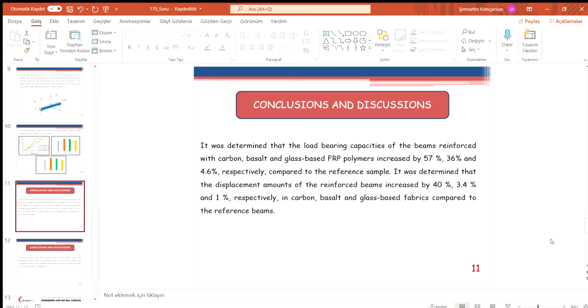It was determined that the load-bearing capacity of the beams reinforced with carbon, basalt, and glass-based FRP polymers increased by 57%, 36%, and 4.6% respectively compared to the reference sample. It was determined that the displacement amount of the reinforced beams increased by 40%, 3.4%, and 1% respectively in carbon, basalt, and glass-based fabric compared to the reference beams.